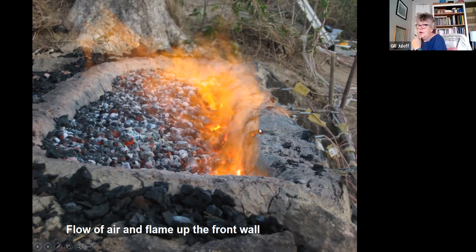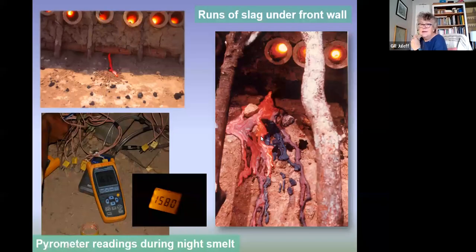So you can't easily see inside the furnace. You can look down the tuyeres, but you don't quite know what's going on until you see that first run of slag. This is the molten waste. It's a silicate. It melts at 1100 degrees centigrade. And once you see that, you know that the right sorts of reactions are taking place inside the furnace.